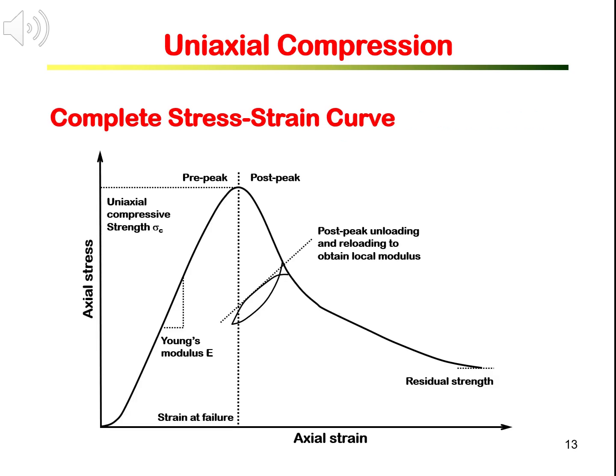A typical and common complete stress strain curve, including the post-peak part, is shown here. The additional information provided by this complete stress strain curve are the post-peak stress strain relationship, the residual strength, and the local modulus at a stress level after peak strength or after failure. The unloading and reloading can be set in the feedback control during the post-peak testing.